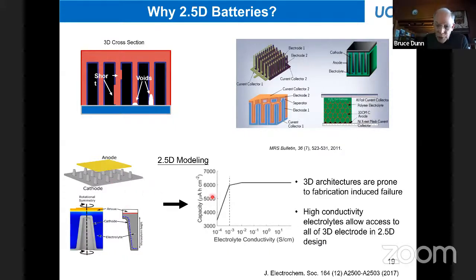And what he really found and told us was that the magic number was to come up with an electrolyte that was 10 to the minus 3 Siemens per centimeter, because at that point the conductivity would be able to penetrate the entire array electrode. If you lose an order of magnitude, you lose the ability to have access to the entire electrode rod. So this is why the 2.5D battery goes about.